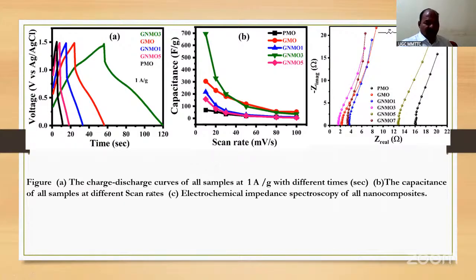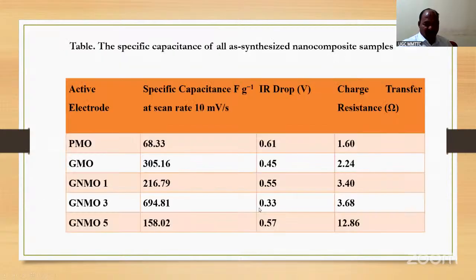Then the as-synthesized samples: electrochemical impedance spectroscopy and the specific capacitance of all synthesized nanocomposite samples, the specific capacitance in farad per gram at this scan rate. So here it increased, then decreased. The charge transfer resistance increased for this.